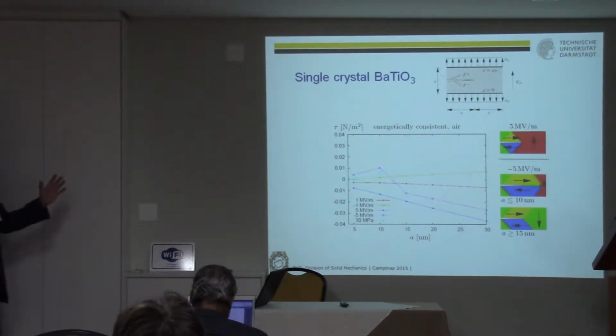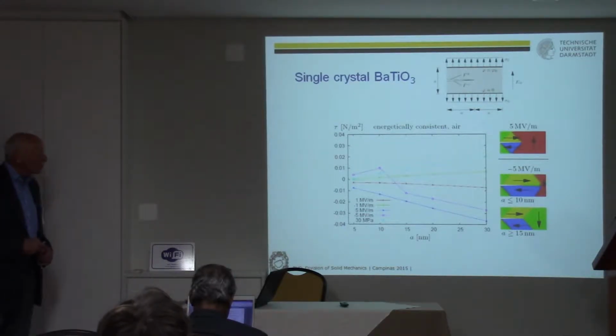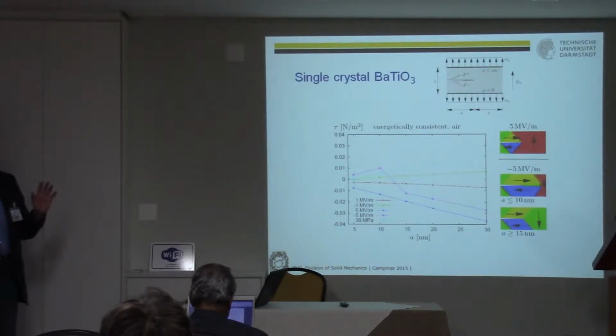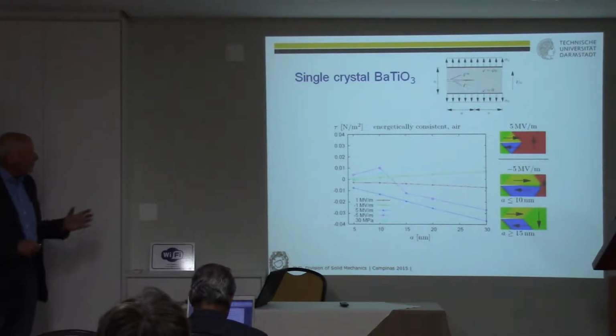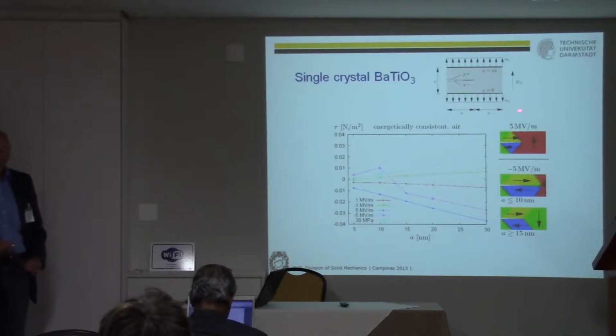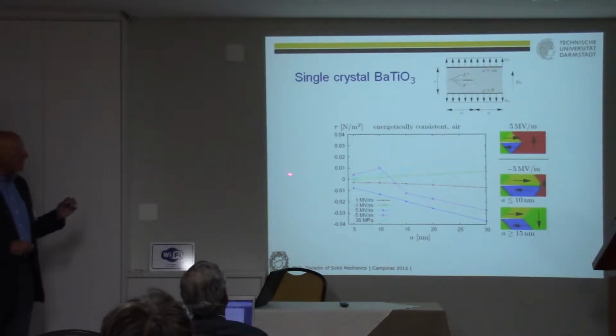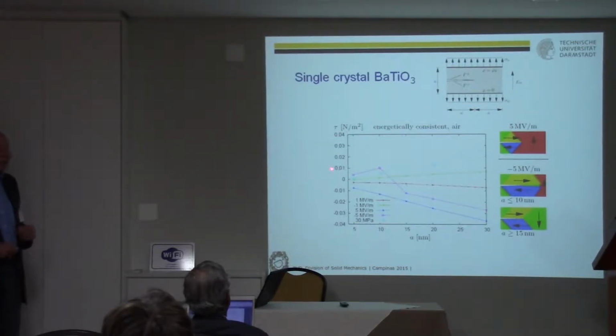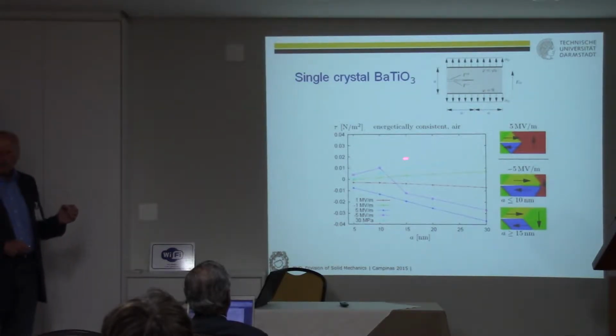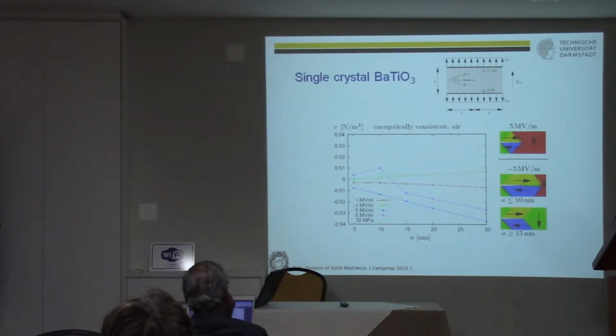The foregoing results were simulations with the material parameters we got a couple of years ago, 5 years, perhaps 6 years. And now, just a few weeks ago, we got new material constants, which were not taken from macroscopic experiments, but from MD simulations and microscopic experiments at single crystals. And so we repeated our calculations.